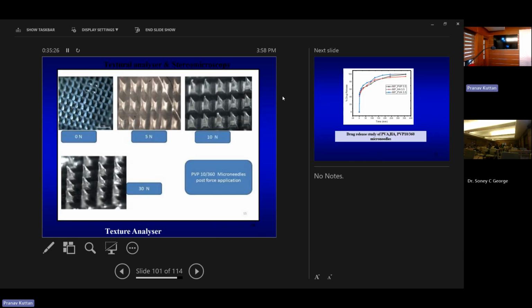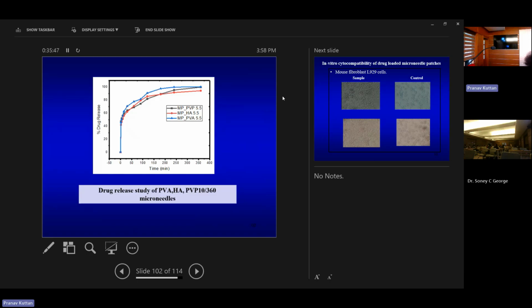So this is again the texture analyzer. We have given different forces, 5 Newton, 10 Newton and 30 Newton. Up to 10 Newton, we can see that only some tips are bent, whereas at 30 Newton the tip is fully bent. So up to 10 Newton force, it is holding without any change. And drug release we also studied. We saw that within 2 minutes itself, about 40% of the drug is released, so it can be used for a fast release of the drug. For faster applications, it could be used.